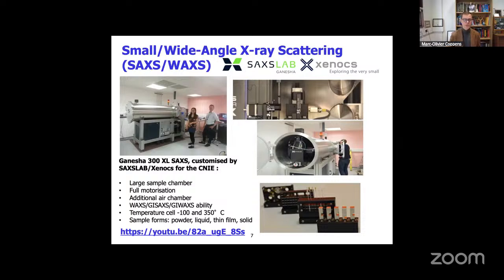I mean, this is an image here of small angle X-ray scattering and wide angle X-ray scattering equipment in our own labs here at UCL by the company Xenocs, previously Sax Lab, and where you can even look in situ also at particle organization and at roughness over a very wide range of length scales. So all these techniques together can give you some insight into the materials, and these can then feed into models for porous materials.